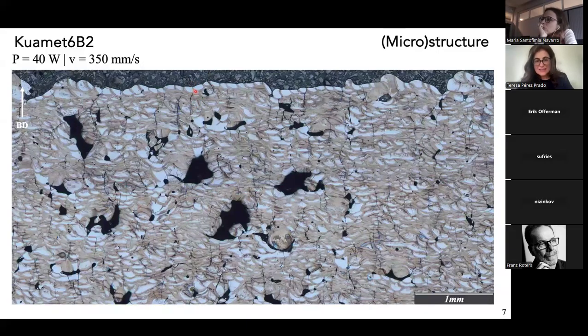And you see that the brown regions are located mostly at the periphery, in the heat-affected zone surrounding the melt pools. Here we can also see very clearly these cracks that I was telling you about, very fine cracks. It is true that even with these cracks, the material can be machined and cut. So it's not that it's mechanically unstable, but of course it's not desirable to have that. At the very least, we want to control crack formation, not just have it without any control.